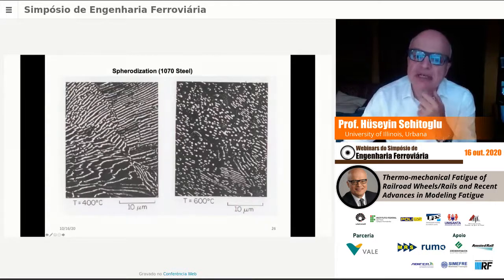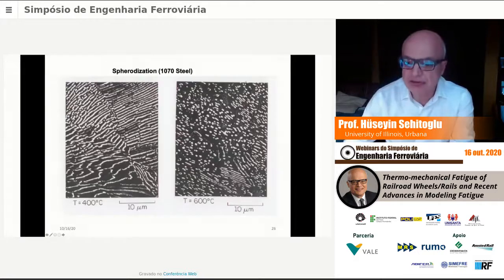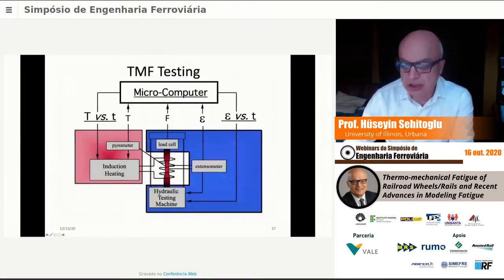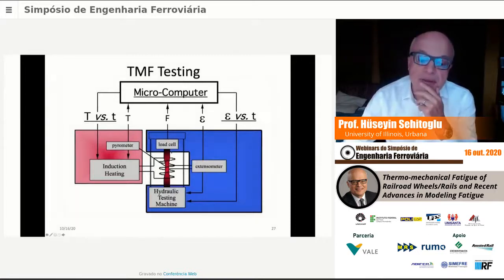Now, the 600 Celsius exposure spheroidizes the material, so microstructurally, the material is no longer a lamellar structure, which is a higher strength structure. So the material actually gets softer with exposure to higher temperatures. And that, I think, should be noted.